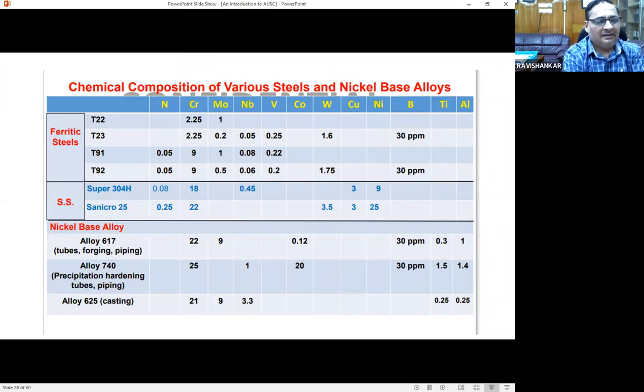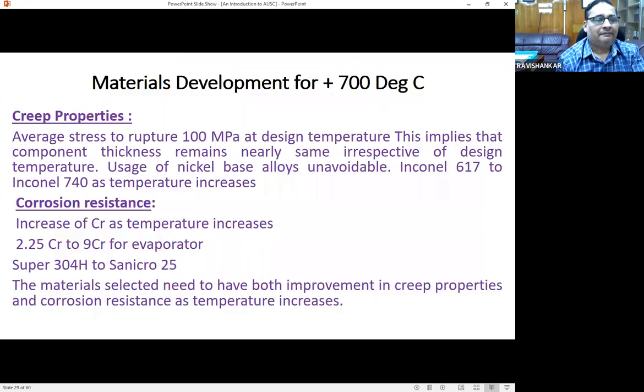And of course, this has led to the high overall cost of the projects, sir, because of the maximum use of nickel-based alloys, which are very expensive in nature compared to the ferritic or regular austenitic steel alloys. Because when the average stress to rupture was taken as 100 MPa at design temperature, to maintain the same thickness for better flow and performance requirements, nickel-based alloys become unavoidable, sir. And 740H was found more suitable compared to 617 because of its excellent enhanced mechanical properties, which resulted in lower thicknesses, and in some cases even a diameter change also, sir.